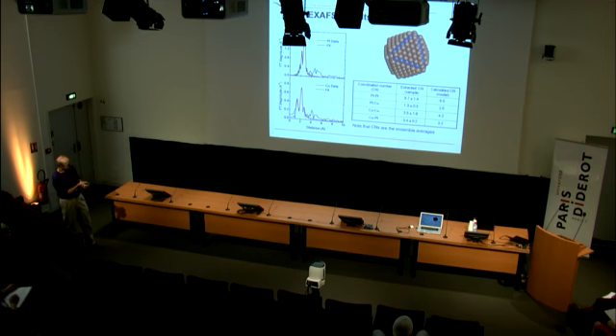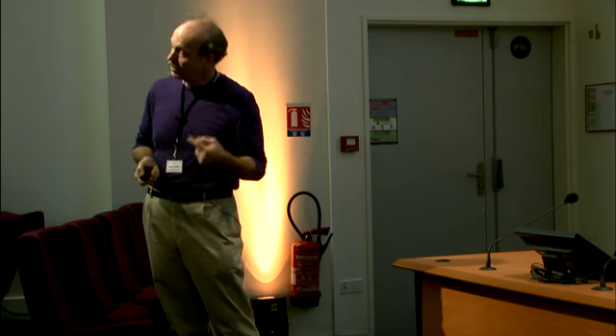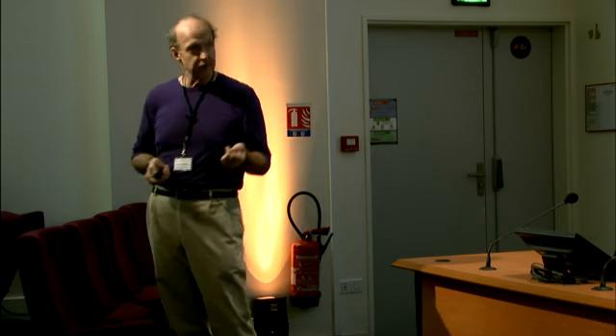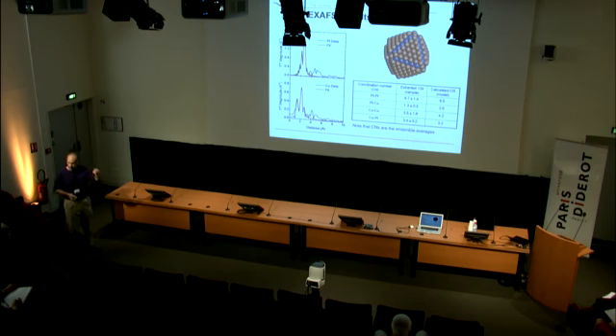So we feel very good about that. And we can look at platinum-copper. Now we're asking for all the platinum atoms, what's the average number of copper nearest neighbors? In our model, it's 2, because those platinum atoms buried in the interior of the particle have 0 copper nearest neighbors, and we're doing a weighted average.